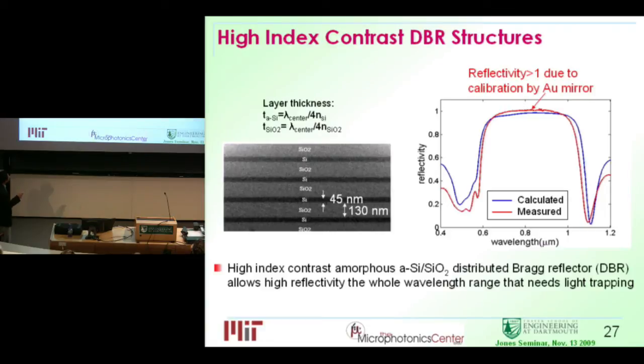for optical path length enhancement. So this blue curve is the theoretical calculation. This red curve is the experimental result. What you notice is this is greater than 1. That can't be right. And what's the reason? Because the reference you use for getting reflection equal to 1 is based on gold. So people assume gold is a perfect reflector, but it's not. DBR is more perfect than gold. So if you make the structures and measure reflectance, you can often measure reflectance greater than 1. So this tells you that this is a very efficient mirror.